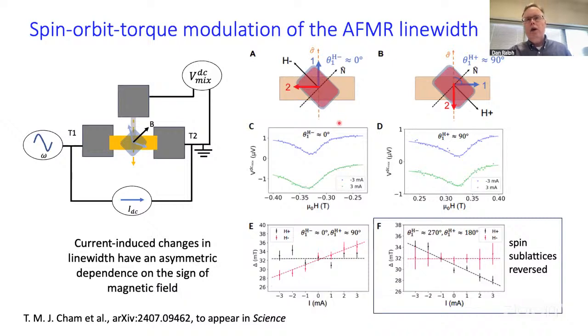And our understanding of what's going on for this orientation is that the spin sublattice adjacent to the platinum telluride channel is perpendicular to the current, which means that spin sublattice is parallel to the spin torque coming from the platinum telluride, so it would be affected by the anti-damping torque. For the opposite direction of magnetic field, again you have a 90-degree orientation between the spin sublattices, but in this case the spin sublattice adjacent to the platinum telluride is parallel to the current, while the spin sublattice at the other layer is perpendicular to the current. Since the spin from the spin orbit torque is perpendicular to the current, the spin sublattice adjacent to the platinum telluride essentially doesn't have the benefit of the anti-damping torque.